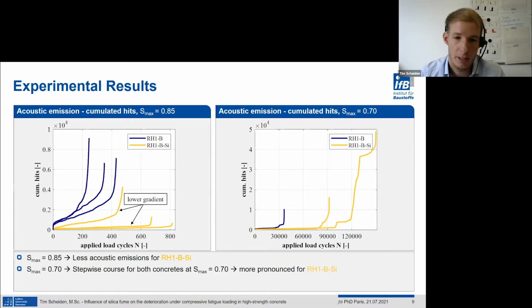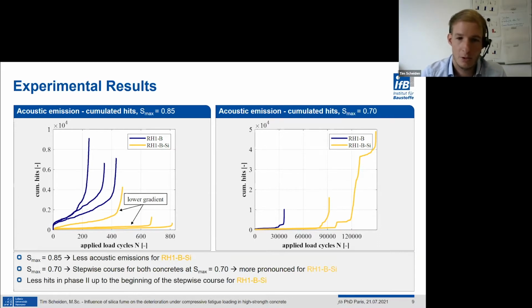correlate with the transition at the compressive strains. At the lower stress level, a stepwise curve is detectable for both concretes, which is more pronounced for the concrete with silica fume. Stepwise curves can be seen here, here, and here. Here it is recognizable that fewer hits in phase 2 up to the beginning of the stepwise curves for the concrete with silica fume are detectable, which is congruent with the higher stress level. So, let's take a closer look at the lower stress level.